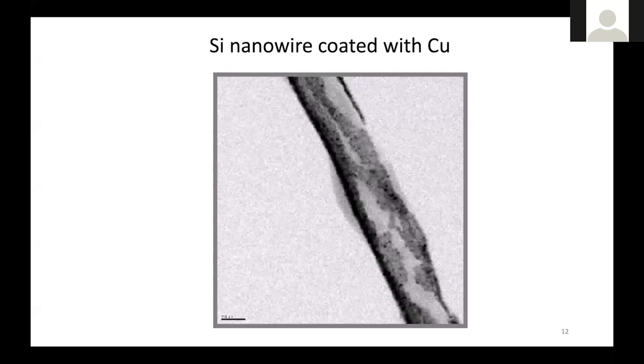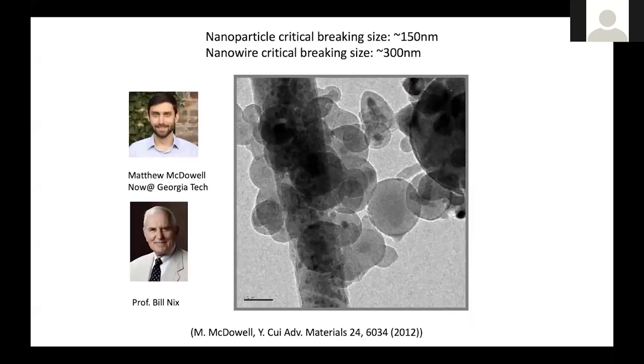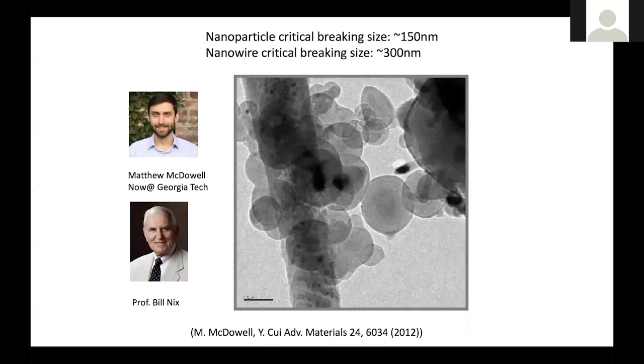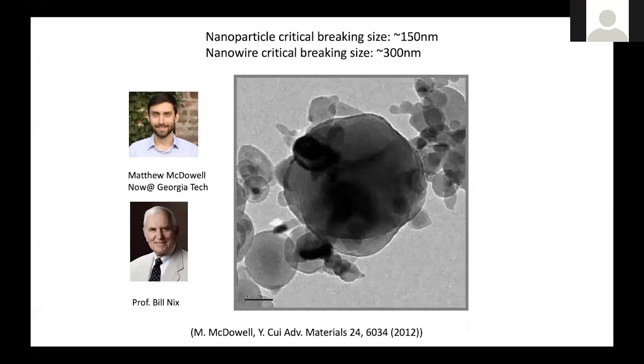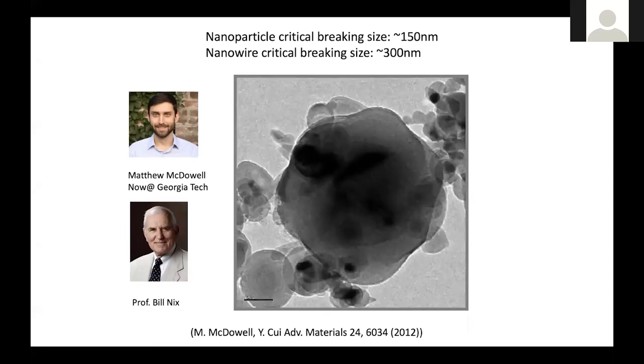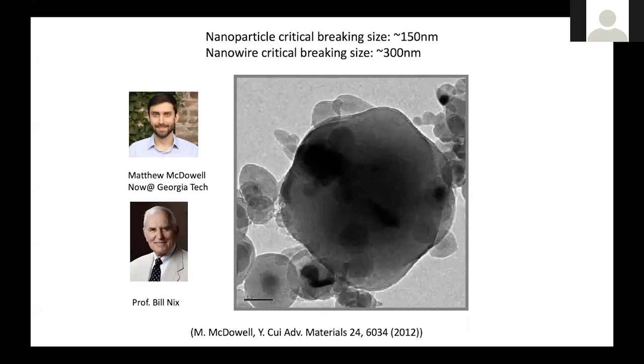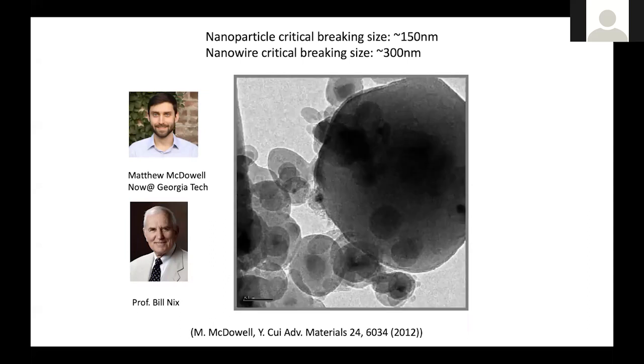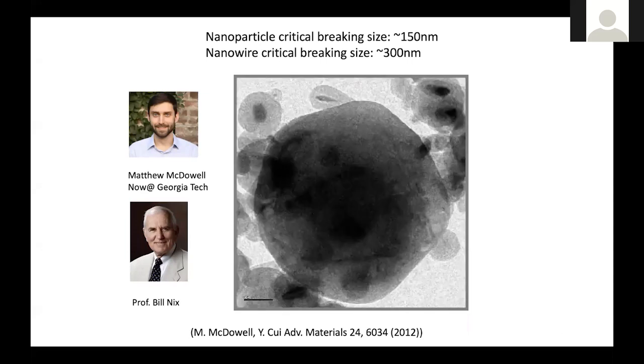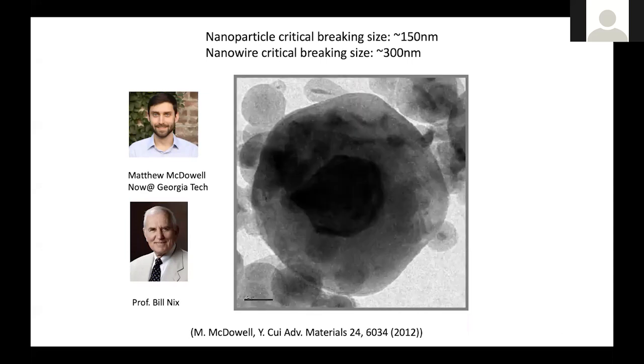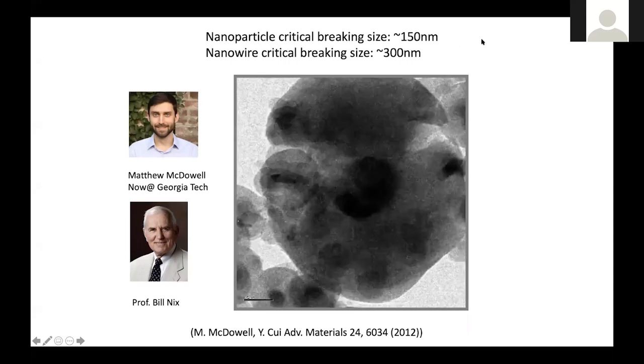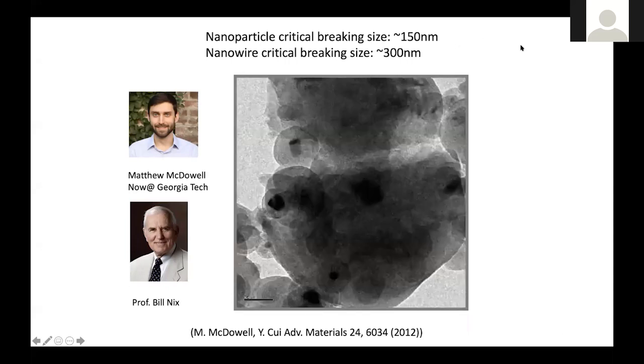Using this technique, we can also look at different sizes and different morphologies. For example, the silicon nanoparticle in the middle you are seeing is 800 nanometers in diameter. Lithium comes in, and the volume of this particle is expanding. After a while, this particle accumulates so much stress that it is going to break. You can see the crystalline core and the amorphous shell right there. Lithium coming in really breaks the silicon-silicon bonds and makes amorphous lithium-silicon bonding. So this change is very, very dramatic.